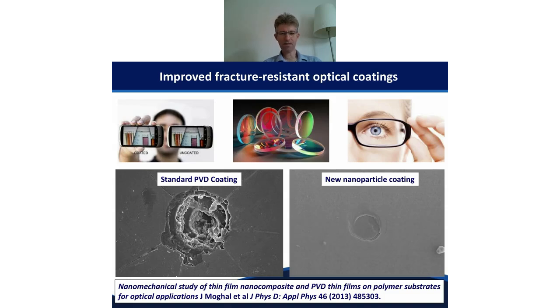One application for this technology is in developing fracture resistant materials. One application here is in optical coatings. These coatings have been designed obviously for their optical properties, and when you do that, sometimes their mechanical properties are less well considered. In this application, the standard physically vapor deposited coating has been subjected to a nano impact test. You can see here a very large impact crater, very brittle fracture, lots of radial cracking, and it's not a very well behaved material under these types of conditions. Our customer here at the University of Oxford developed a new nanoparticulate coating, which was softer, but much less susceptible to this brittle fracture mode. So it shows that you can really use this type of technology to design better materials for these extreme environments.